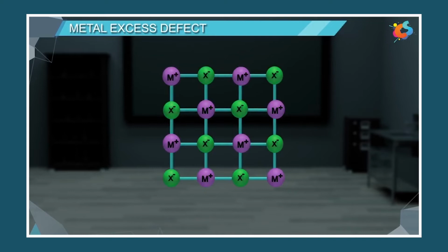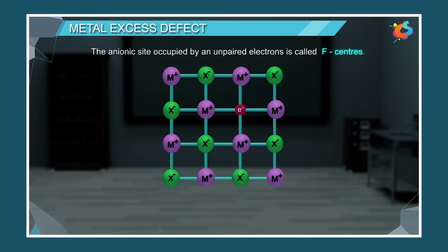The sodium atom gets associated with the lattice and settles in a normal cation site, creating an equivalent number of anion vacancies in the crystal. These sodium atoms subsequently ionize into Na+ ions and electrons. The released electrons occupy the anion vacancies. These free electrons, which are capable of absorbing light, impart yellow color to the compound.